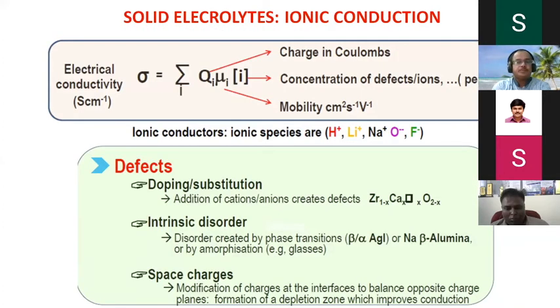Okay. If you look at the very basic equations, solid electrolytes in ionic conduction, the electrical conductivity depends on 3 factors. One is sigma equal to summation over i of q_i, n_i, mu_i: q is the charge in coulombs, n is the concentration of defects per ions, and mu is the mobility. So ionic conductors, so ionic species are either a proton conductor, lithium ion conductor, sodium ion conductor, oxygen ion conductor, or fluorine ion conductor. So cations and anions.